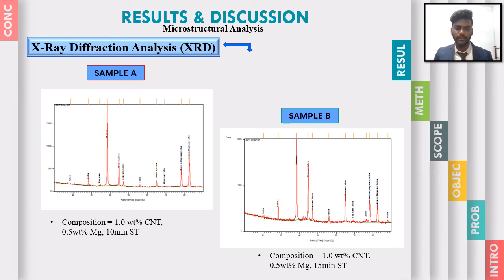15 minutes. So the XRD shows that sample A has a very optimal and stabilized graph of carbon, while sample B has a very high peak of carbon and also inconsistent peaks in the graph, showing that carbon has diffused. So A can be very good resistive towards wear and also in mechanical properties, while B should have some other flaws, and unpredicted failures can occur due to the unstable XRD flow of peaks.